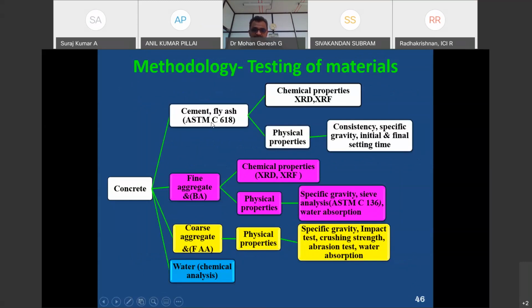For the fly ash, we have used the ASTM C618 for checking the physical properties of fly ash, and chemical properties like XRD, XRF we have done, and particle size distribution. Everything we have done, with consistency, specific gravity, initial and final setting time of the cement we have done it.